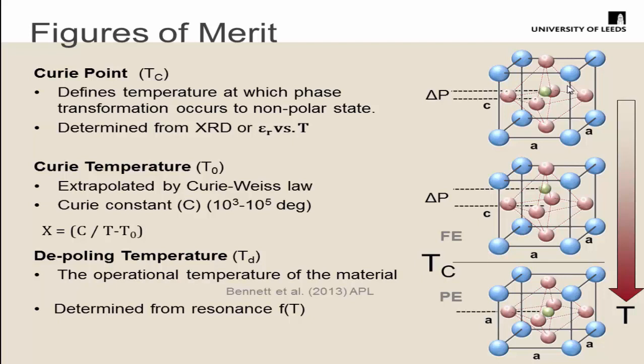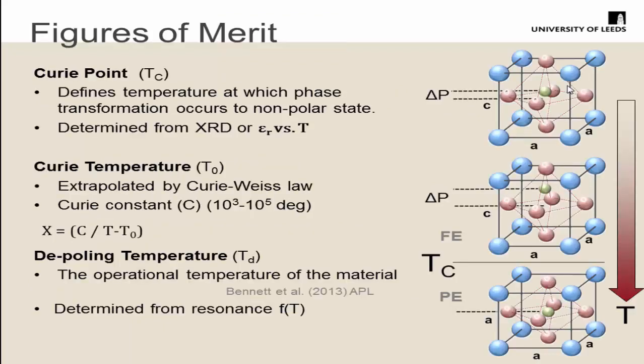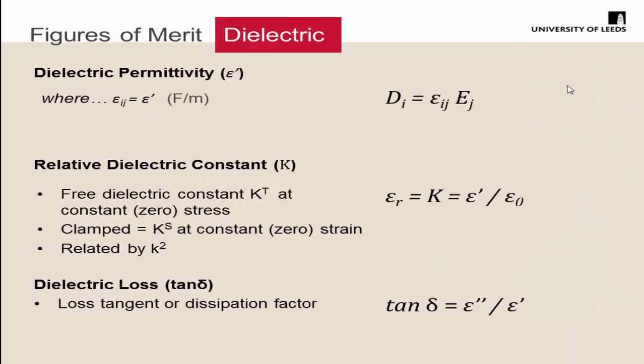This is captured quite well in a paper by Jim Bennett, who's in the audience. We're also looking at dielectric permittivity and measuring it as a function of temperature to determine our Curie temperature. We're determining these using different methods: depoling temperature from resonance or strain-field type measurements, and the Curie point from X-ray diffraction or permittivity-temperature plots.